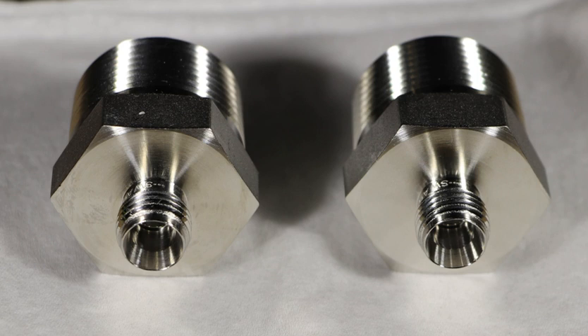Ferrous materials, including steel, may be somewhat protected by promoting oxidation and then converting the oxidation to a metallophosphate by using phosphoric acid and further protected by surface coating. As the uncoated surface is water-soluble, a preferred method is to form manganese or zinc compounds by a process commonly known as parkerizing or phosphate conversion.